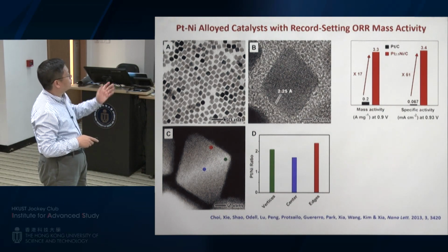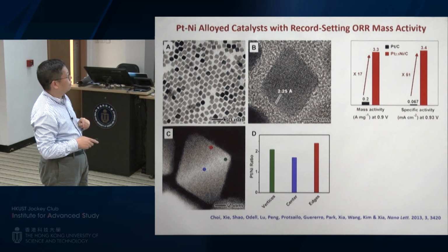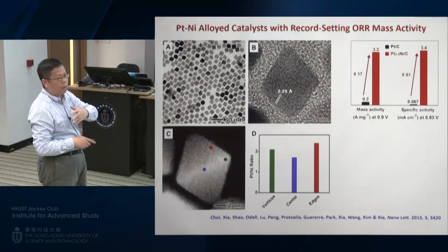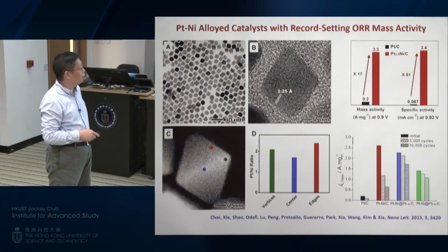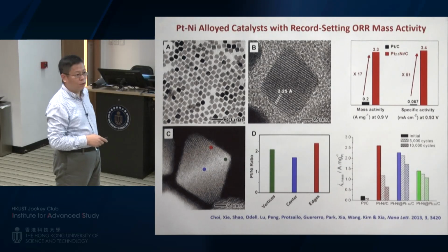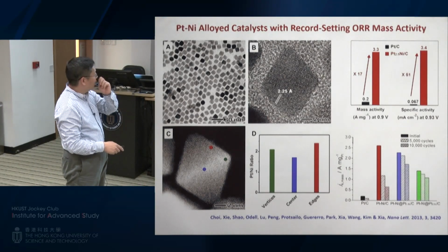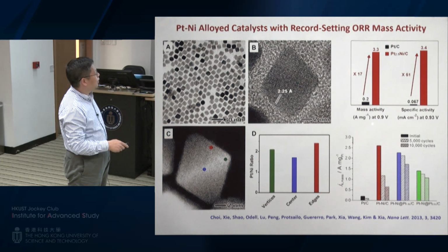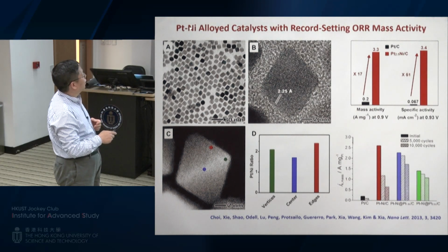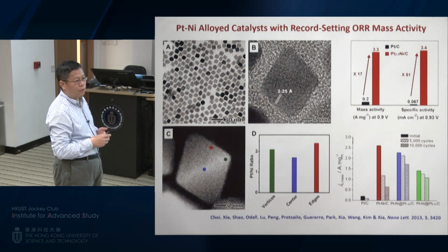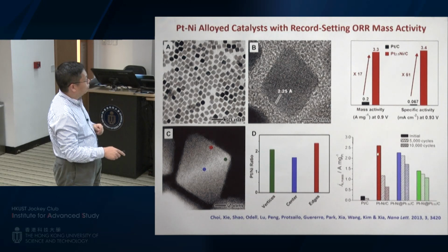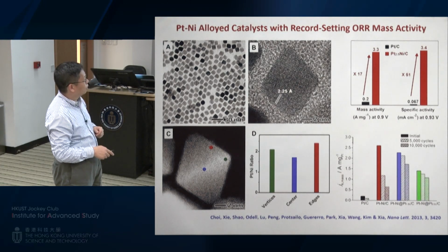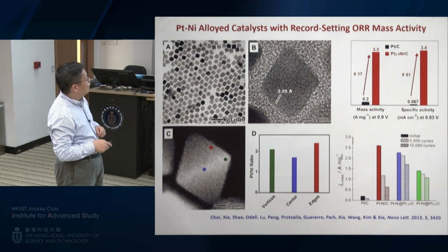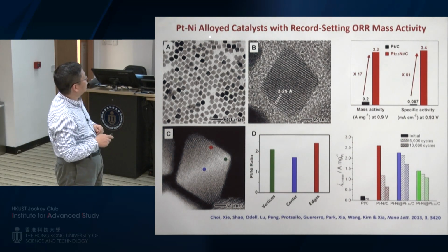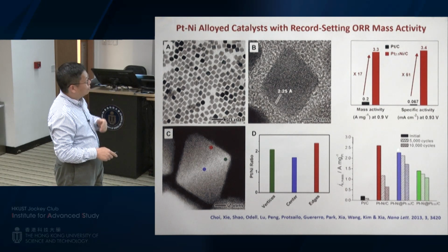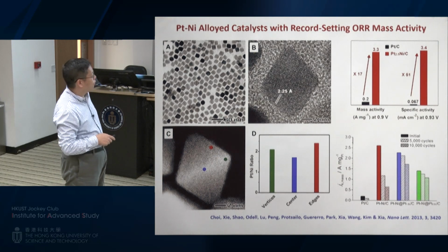And we thought this system could solve the problem, but unfortunately we had some more study, and we also collaborated with GM after Minghua left. We did some tests. We found this system not so easy to put in commercial use because their durability turned out to be a problem, and their activity will drop very significantly, because Pt nickel is an alloy, and nickel is so reactive, it will come out very easily. So their activity will drop quite significantly over different cycles of test. We also tried to stabilize it by putting some platinum shells around it. There's some improvement, but overall, it may not be very ideal.